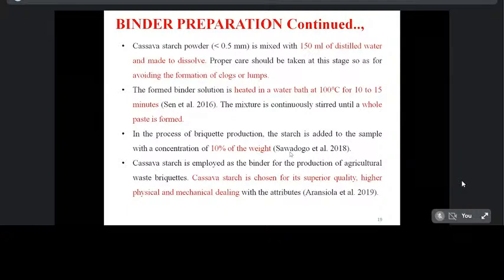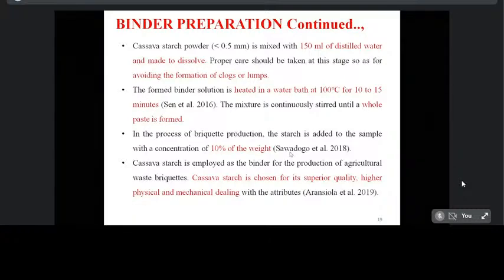Okay, so the less than 0.5 mm starch is mixed with 150 ml of distilled water to dissolve. While preparing this cassava starch binder, proper care should be taken at this stage to avoid the formation of clogs and lumps. The formed binder solution is heated in a water bath at 100 degrees Celsius for 10 to 15 minutes as per Sen et al. 2016. This mixture is continuously stirred until a whole paste is formed. It means the semi-solid formation.